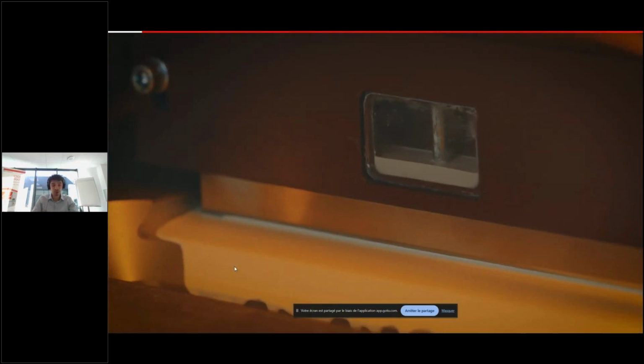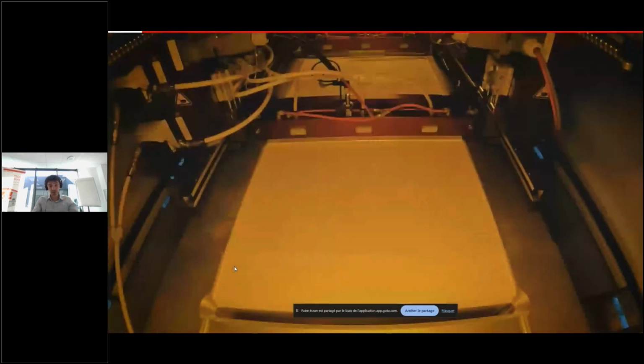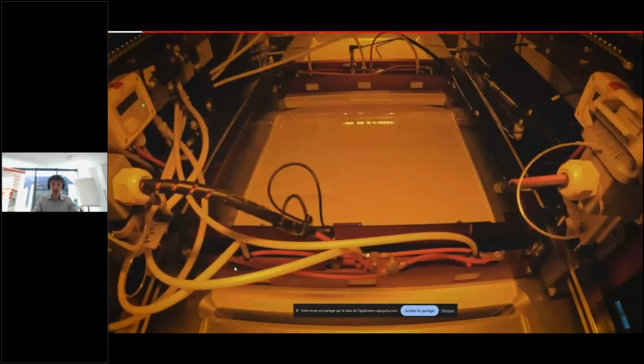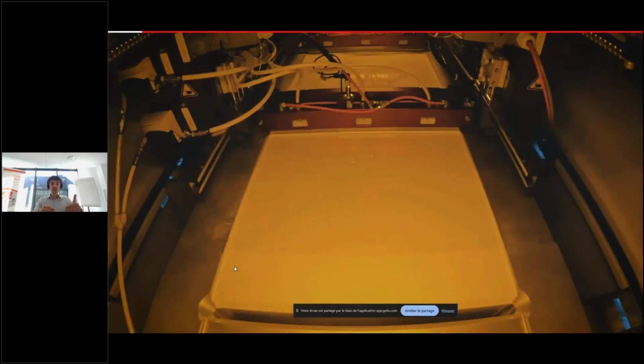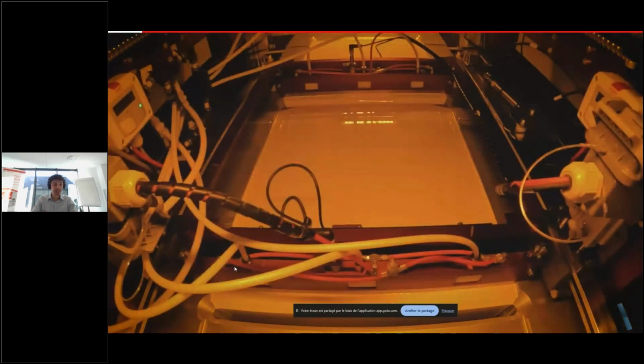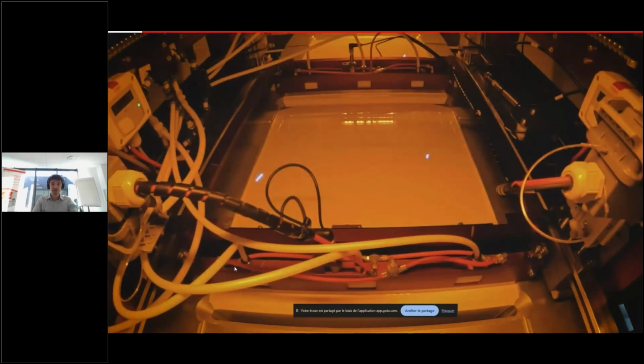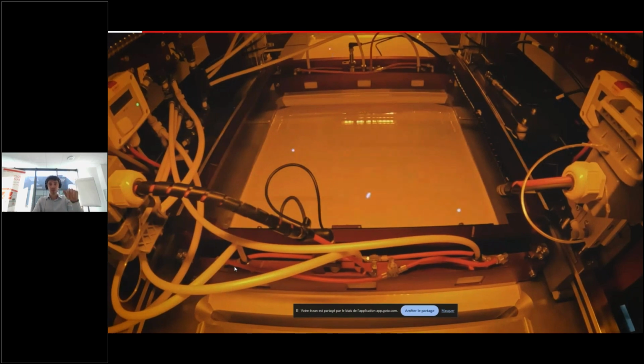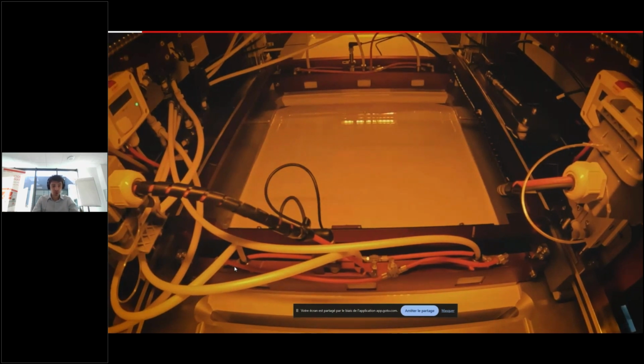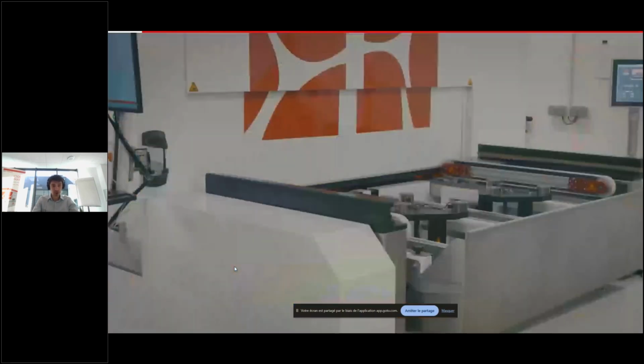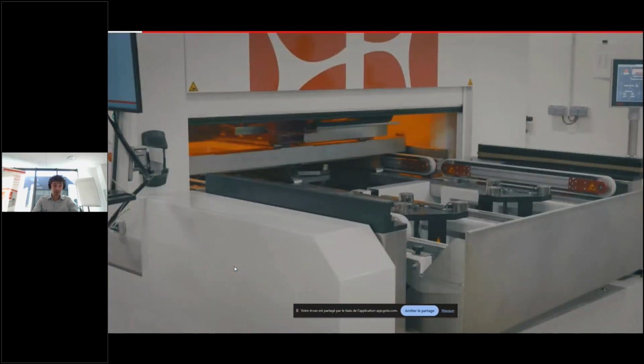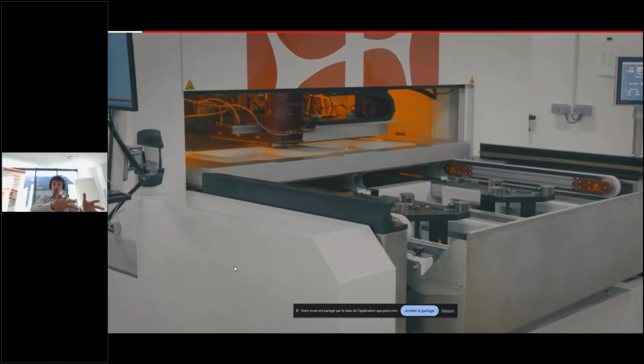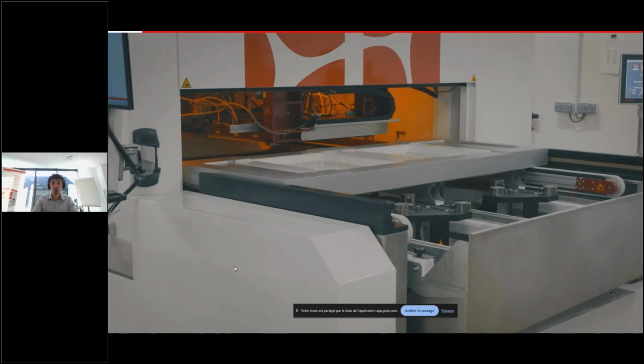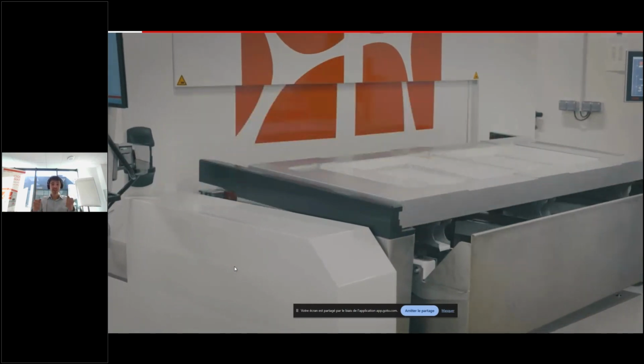So you have the slurry. In this case, as we are printing a zirconia cell, the slurry is zirconia with 8% yttrium. We have the 2 printing platforms with the 2 recoater systems, and a total of 3 plus 3, 6 UV lasers on the top in order to decrease as much as possible the printing time. After, automatically the printing platform goes out to the unloading system.